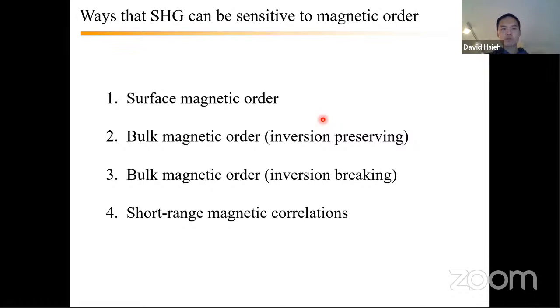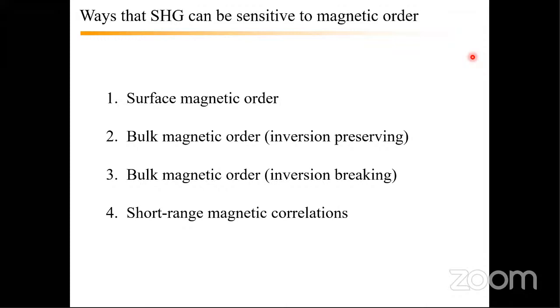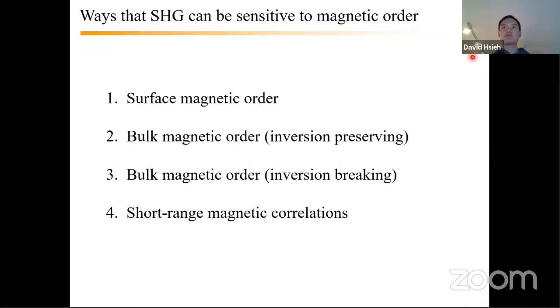Hi, Chandra. Hi, David. In relation to these anisotropy patterns, what is the beam diameter of your, the best, smallest beam diameter that you work with? Yeah, so it depends on what we prioritize, but if we just want small sizes, we can go to close to the diffraction limit, which would be on the order of a micron. That's the best. We're always above the diffraction limit.